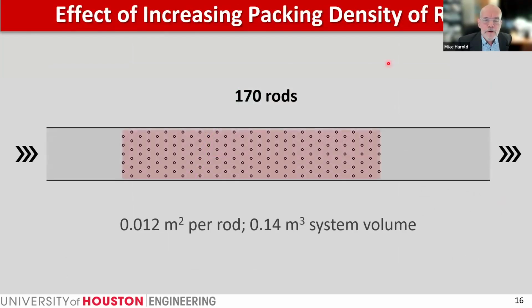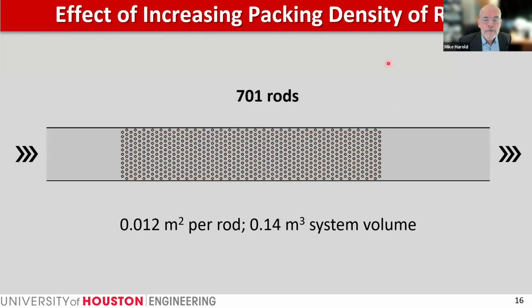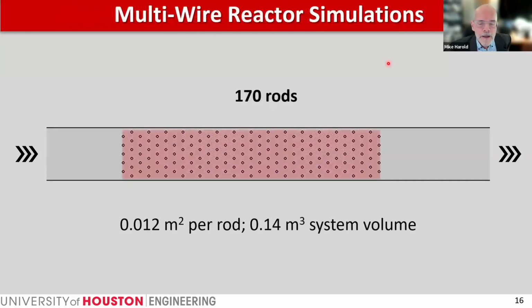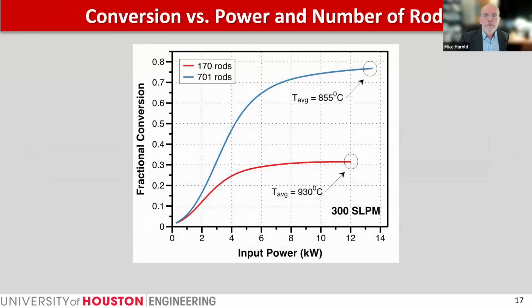Now, what happens if we increase the number of rods from 170 to about 700? So this is a kind of experiment on the computer where we look at a more densely packed tube with now 700 rods to increase the productivity of the same volume of reactor. Here's the results comparing about a factor of 3 or 4 more rods, going from a conversion of a little over 30% at this flow rate for the 170 rods to a conversion approaching 80% at a power setting of about 13 or 14 kilowatts.